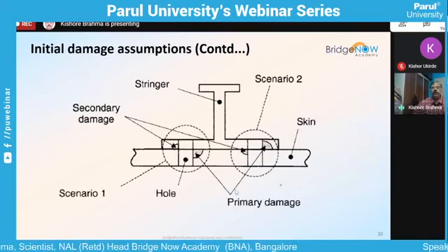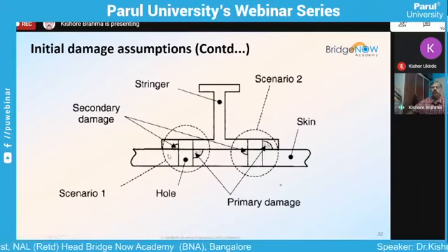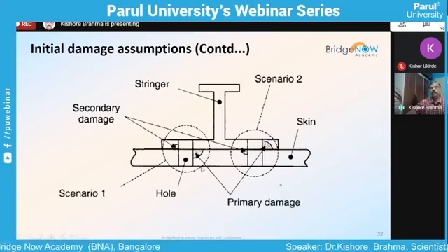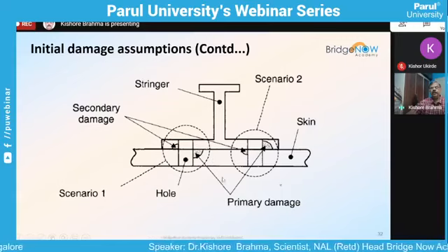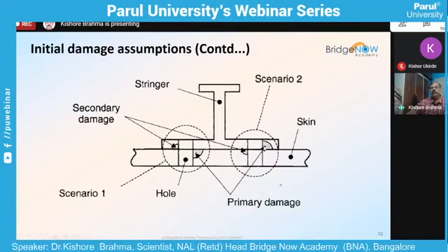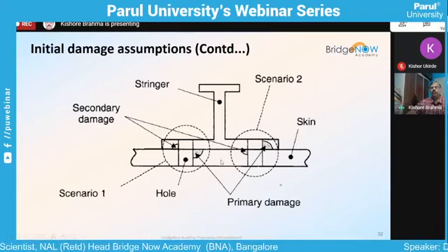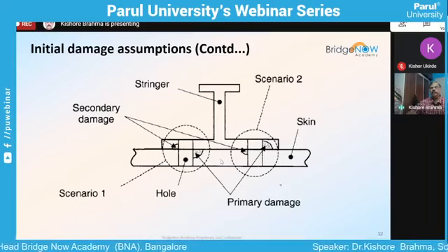This is an example of a stringer and skin combination. As part of the procedure, one has to assume both the quality flaw and the rogue flaw to start with, even though there may not be a flaw. If you are assuming that the skin is primary structure and the stringer is secondary, then you have to use primary damage in the skin and secondary damage, that is a quality flaw, in the stringer. Or one can assume primary damage in the stringer and quality flaw in the skin. So there are two scenarios possible for the stringer-skin combination, and one has to make such assumptions for crack propagation as part of damage tolerance evaluation or analysis, to evaluate its capability.